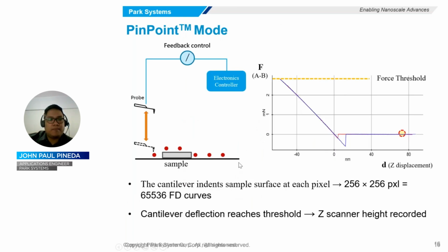Okay, so now let's proceed with pinpoint mode. During operation, while measuring sample morphology, the XY scanner stops at each acquisition. And during this pause, the Z scanner takes a rapid FD curve with finely controlled force, distance, and contact time between the tip and the sample.